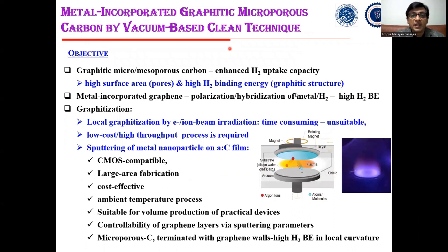Therefore, we are planning to fabricate a metal incorporated graphitic microporous carbon by a vacuum-based technique. The objective is that in the graphitic micro or mesoporous carbon, we can have very high surface area from the pores and very high H2 binding energy in the graphitic network, which will enhance the hydrogen uptake capacity. On the other hand, the metal incorporation will increase the polarization and hybridization of metal and hydrogen to increase the hydrogen binding energy. But the graphitization process by vacuum-based techniques generally uses electron beam or ion beam irradiation on some carbon films or amorphous carbon films, which is highly time consuming, therefore unsuitable for volume production.